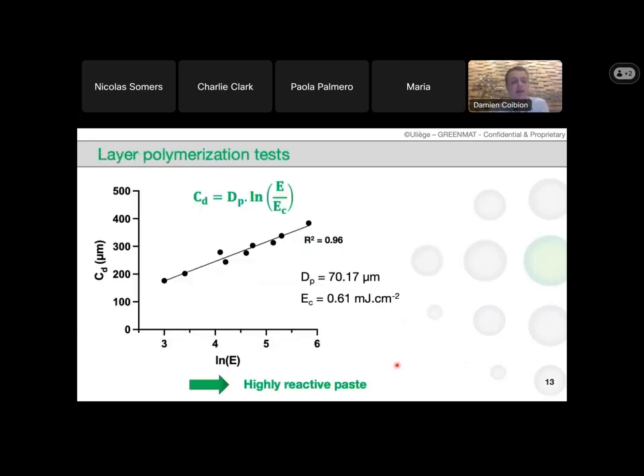The next characterization that we performed are tests of polymerizations. So we are printing only one layer at a time, and we can measure the thickness of this layer compared to the energy density that we are applying on the paste. The energy density is mainly dependent on the time, the scanning speed of the laser, and its power.